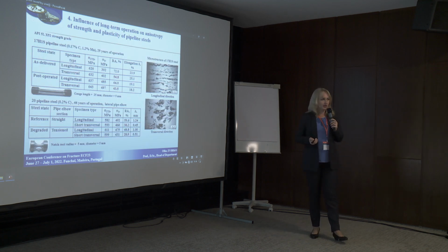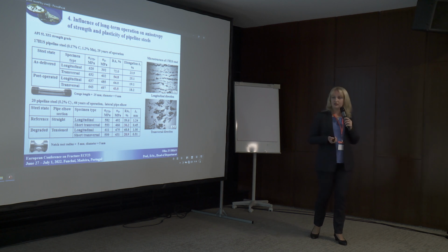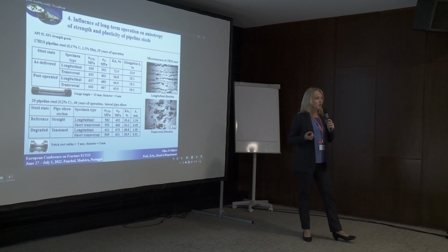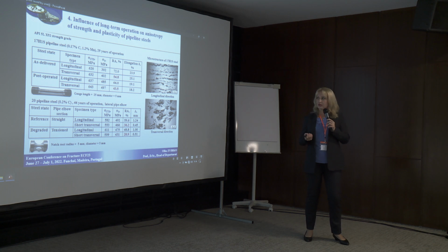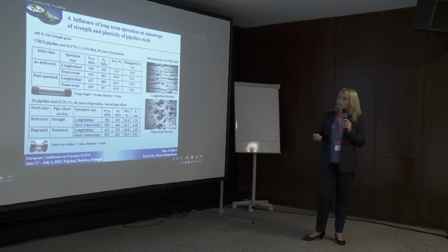Anisotropy of mechanical properties of rolled pipeline steels is a well-known phenomenon, and here you can see such a typical microstructure of a rolled pipeline steel. However, it's important to know whether long-term operation influences this anisotropic mechanical behavior. And this research question was studied for two pipeline steels of X52 strength grade after operation, and also in as-delivered state and reference steel.